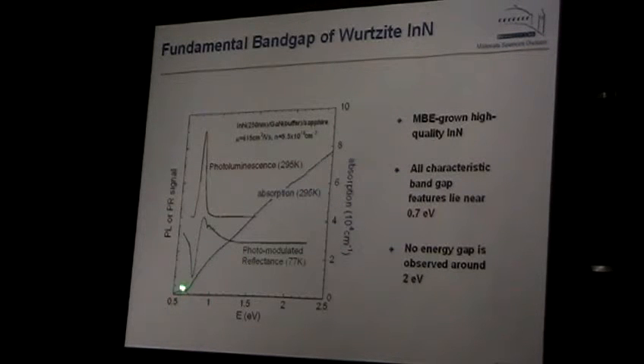So we have the signature of the energy gap at 0.7 electron volt. This is absorption. Absorption is increasing starting from 0.7. We see light emitted at around 0.7. And also we see so-called photomodulated reflectance, which is another indication that there is an optical transition at this stage. So that changed the picture dramatically.